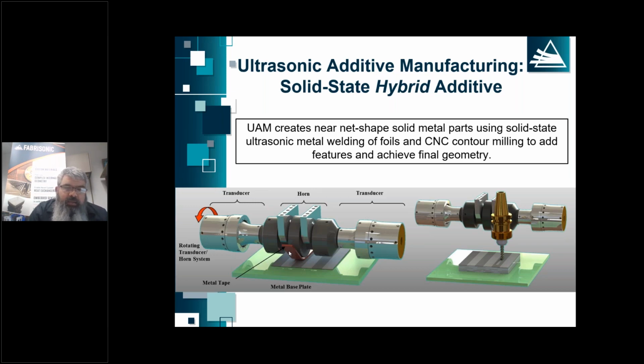Because we're not creating any heat during the welding process, we don't really change the base material properties of the incoming feedstock. We're not changing grain size, we're not changing precipitate size. What's coming in is going out. On the right-hand side, we have depicted a CNC mill. Again, from time to time, we can come in with the mill and create both that internal and the external geometry. Pretty much every surface in an ultrasonic part is going to be touched by a mill.